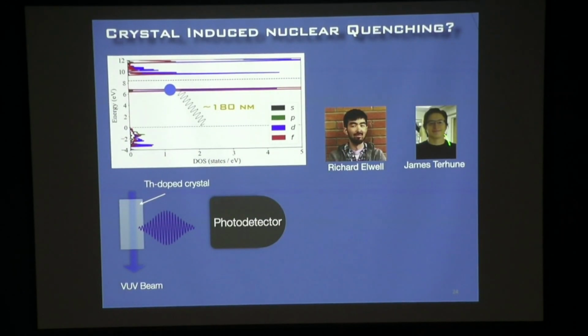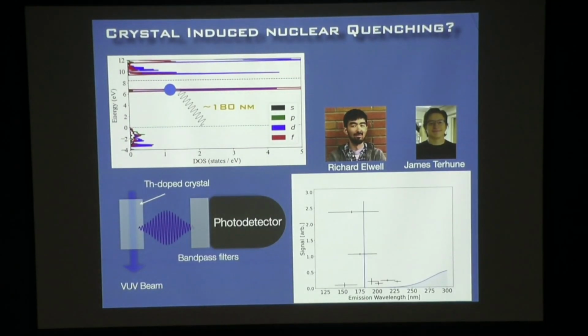And Ricky and James were the grad students working on this. We didn't have enough signal to really put this into a spectrometer, so they basically took every filter we could get and took different combinations and then did a Gaussian deconvolution and backed out the spectrum mathematically. And what we found was this blue trace here. Red of 225 nanometers, this is just the phosphorescence of the crystal. We already knew this. You could just take the crystal, put it in a grating spectrometer, and integrate. And the crystal glows a little bit in the UV because it's radioactive.